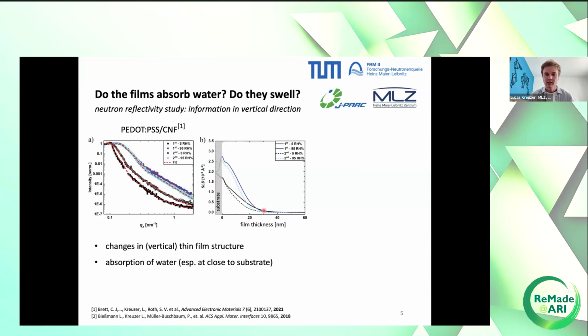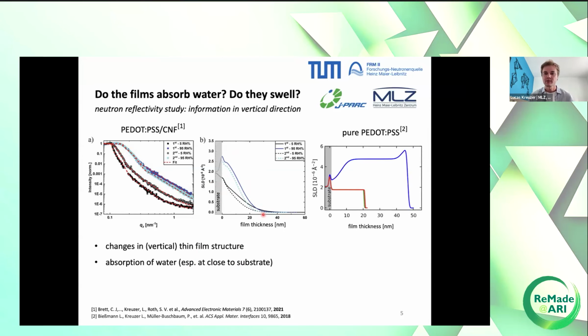Another thing we see is that the film thickness actually remains more or less constant in a dry and in a humid environment. And this was really surprising because we measured the pure PEDOT:PSS films a couple of years earlier, and there you see a massive swelling. So a swelling factor of 2.5 or even more from the dry to the humid PEDOT:PSS film.